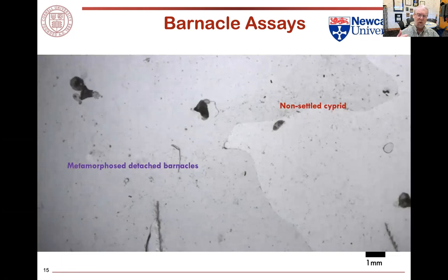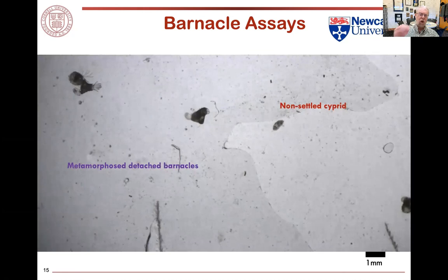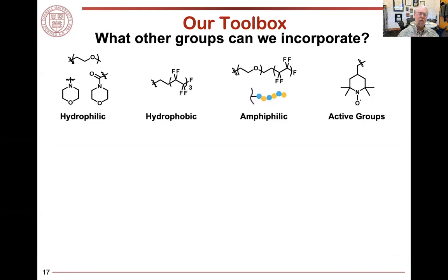But over time, if you push and force them to attempt to reattach, the biology allows them to change their adhesive, become much more effective, and eventually they do stick. So we're close, but we're not quite there. What we think we need is an additional strategy for making these materials resistant to hard foulers. We've been trying to expand our toolbox between the PEG unit and the PDMS as an amphiphilic material and incorporate other functionality. So we're looking at alternative hydrophilic groups, alternative amphiphilic groups.